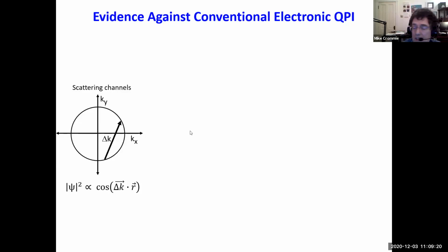Now, quasi-particle interference occurs when you have a system where you can have electron scattering between two energy conserving states. And then, like I show here in this little diagram, that leads to quasi-particle interference patterns that have a wave vector equal to this scattering wave vector. So you get a quantum interference pattern at that wave vector. And so you can calculate these quasi-particle interference patterns for different materials.